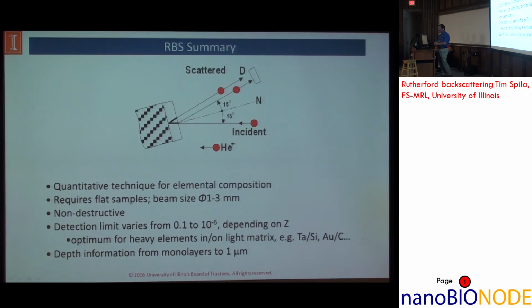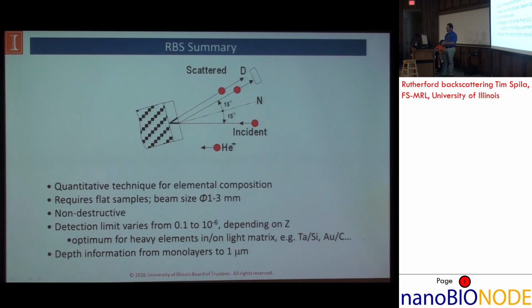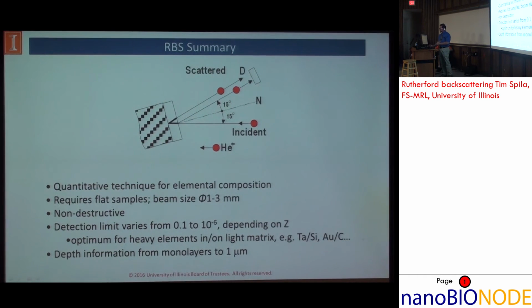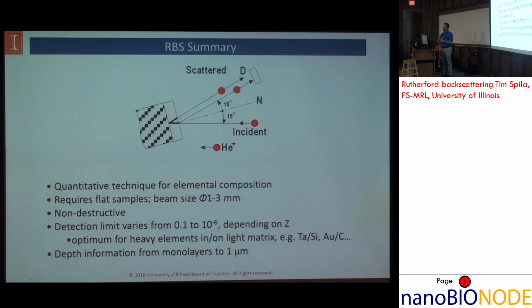So to summarize, RBS is a quantitative technique for elemental composition. Does require flat samples, and the beam size is large, 1 to 3 millimeters, but it can be non-destructive. For polymer type layers, you will burn your layer, but for metals and semiconductors, it's basically non-destructive. The detection limit does vary from 10% down to 10 to the minus 6, but that's very dependent on the atomic number.